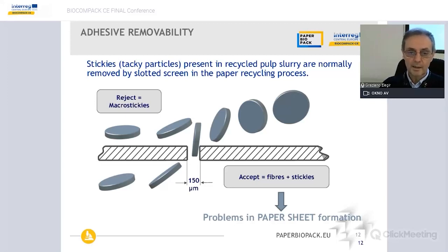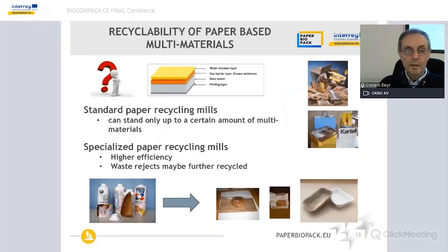The issue is that these tacky particles, when they disintegrate in the first step of the recycle line, are present in the recycled pulp slurry, and normally they are removed by a slotted screen. During the recycling, we have different sizes of this screen, but the smallest ones are about 150 microns, and if these adhesives are smaller, they end up getting into the accept with the fibers, and in the end they create a problem during paper sheet formation, either during the process and also for the quality of the final products. So I hope you understood more about what the issue is.